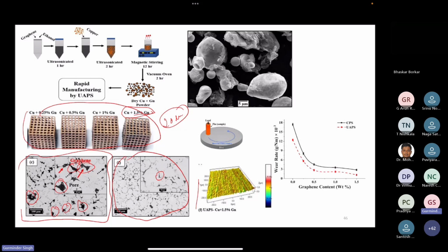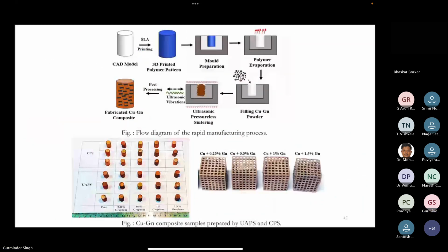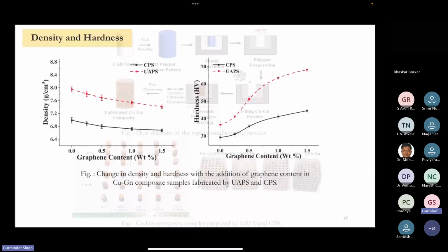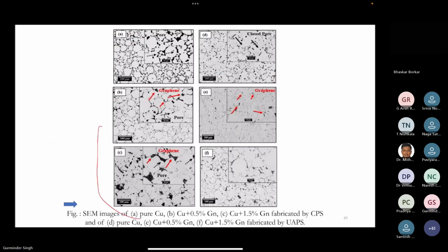We have tried it for tribological properties also, and the ultrasonic assisted 3D printing of copper graphene gives us better properties in tribological terms. Similarly, we have used this process to make these forms also and tested mechanical properties. As compared to the conventional process, the ultrasonic vibration process is giving better graphene distribution among the surface of the 3D printed part.